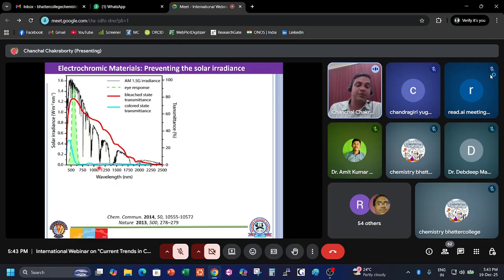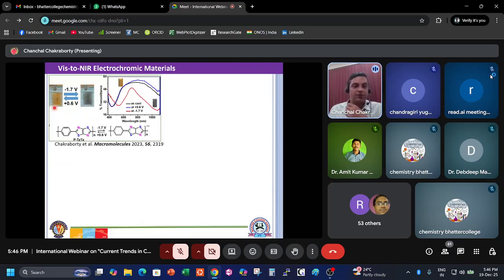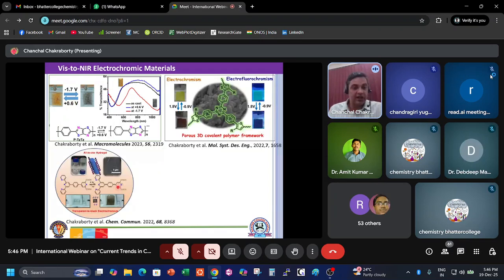So with this kind of strategies, we have developed a few visible to NIR electrochromic materials by means of conjugated polymers. We used a thiazole group that is redox active, and that can give a yellow to blackish color in electrochromism by means of voltage. Also we developed a porous 3D covalent polymeric framework that shows a yellow to brown color change in electrochromism, and this is associated with electrofluorochromism, where the electrochromism is associated with a fluorescence change of the film. And also we developed small molecules and all-in-one gel.